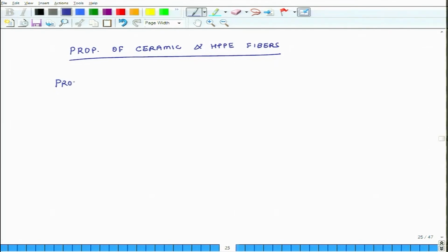So, we will again construct a property table, and let us look at different fibers. The first one is alumina, Al2O3, the second one is silicon carbide fiber made through the CVD process, the third one is silicon carbide made through the pyrolysis process, and the fourth one is HPPE. Okay. So, let us look at diameter in micrometers or microns: 15 to 25, 140. So, silicon carbide fibers are fat, they are thick, but if you make them through pyrolysis you can make them really thin. So, 10 to 20, and this is about 38-40 microns.